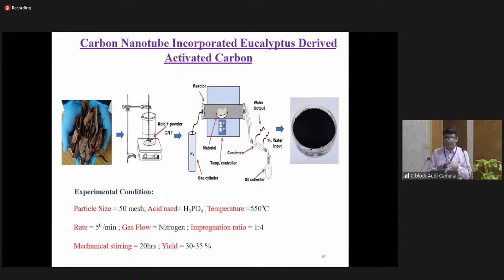So in that experiment, what we did, we have eucalyptus bark, and then you put the bark, and at the same time you are putting the acid as an activation agent. At the same time, you are also adding the carbon nanotube, and then you're mixing. Now you have a material of carbon nanotube, eucalyptus bark, and the acid. That material has to be activated in the carbonization furnace. Okay. So when the activation reaction is taking place, all three things are available. So when the activation is taking place, the carbon nanotube as well as eucalyptus bark, the interaction is taking place, making a better possibility of improvement in the performance in terms of percentage removal or in the time reduction.